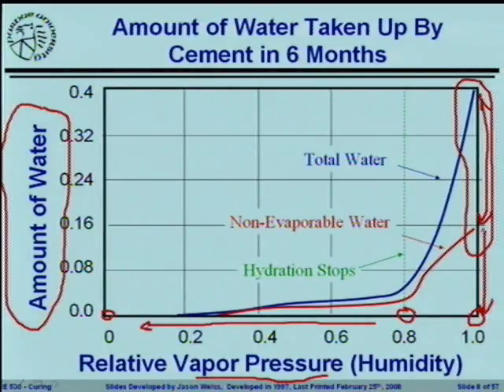So this tells us that if we want the entire concrete system to be reacting, we want the cement to be hydrating, we need to have a relatively high relative humidity. Right? We need to keep this relative humidity high. Now in concrete, we're not going to get up to 100%. There are salts in the pore solution which cause us to have to look at these ideas of relative vapor pressure. We can bring in Raoult's law and things like that. But the basic idea is if we are above about 96, 97, 98% relative humidity, we have a system that's nearly saturated. There's enough water in there to be participating in the reaction, and we're going to get the most reaction that's taking place in that cement.